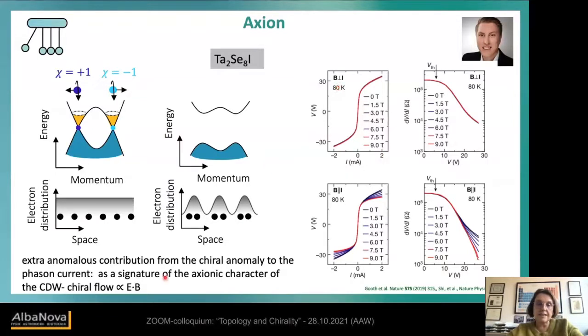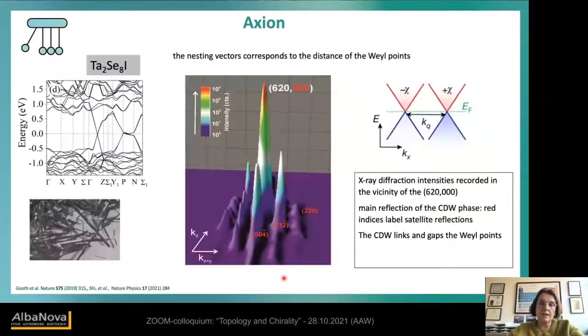And you see again, the E dot B term is very important. So we have to measure the magnetic field perpendicular to the current, and we don't see anything. And if we measure the magnetic field parallel to the current, we see a negative magnetoresistance effect like we have in a Weyl semimetal. So we are now looking for light-matter interaction experiments in this direction, and so on, to have further proof of the axion phason in this material. But we also have ideas about other materials where we can find similar effects.